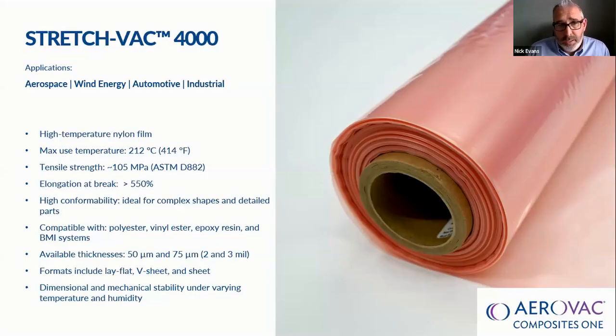It's available in the common formats such as lay flat tube, V-sheet, and standard sheet product, and we're also able to weld and heat seam this product to either wider widths or some complex shapes as well. So this is now a film that's stable under those tough environmental conditions, and also gives really good mechanical properties for tensile strength and elongation.